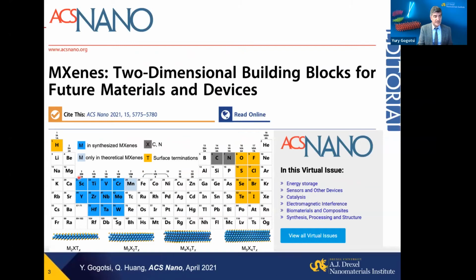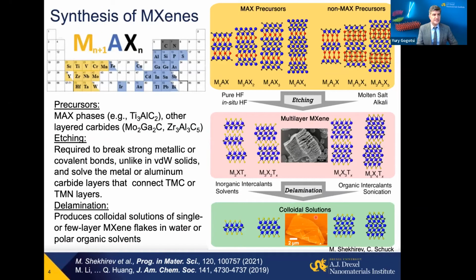By now, we have more than 30 stoichiometric MXenes produced, and more than 20 solid solutions published, which include atoms of transition metals marked here in blue, carbon, nitrogen. Surface termination can be oxygen, OH, chalcogens, halogens, and they come in multiple structures. If you multiply the number of atoms by the number of structures, carbon, nitrogen, you end up with more than 100 stoichiometric compositions. Add 10 different surface terminations demonstrated so far, and you end up with at least 1,000 materials with a defined composition. And if you consider solid solutions, it really becomes an infinite number of materials.